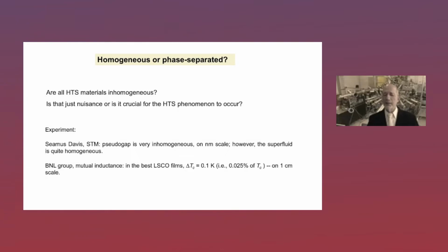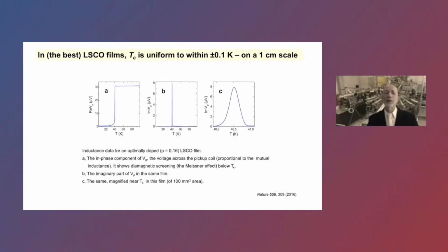Now, the STM scale is typically 100 nanometers or less. But my group has shown mutual inductance data showing that in the best lanthanum strontium cuprate films, the variations of Tc are less than 0.1 Kelvin out of 40, which is less than 0.2%. And that's on the scale of 1 centimeter. Just to show some figure, these are raw experimental data. They were not even normalized by dividing the transmission by that of the substrate, and you can see that the sharpness of this peak is a fraction of a Kelvin, and if we had two parts with Tc differing by more than 0.1 Kelvin, then we would see splitting of this peak, which is not seen.